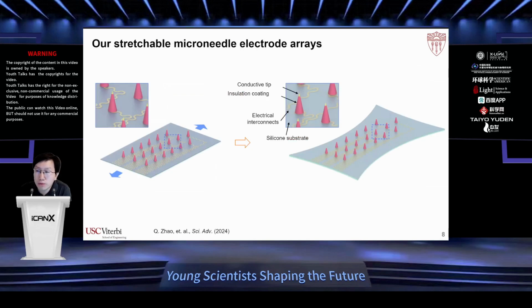Here we have an array of rigid microneedle electrodes with their tips exposed for targeted sensing and stimulation. And how can we make rigid microneedle electrodes stretchable? We use serpentine interconnects, which is a commonly used structure design in stretchable electronics. Each microneedle is electrically connected to a serpentine interconnect, which is then connected to external electronics. The microneedles and the serpentine interconnects are bonded covalently to a stretchable elastomer substrate, so that when we stretch, the serpentine interconnects can deform, rotate, and twist, while keeping the needles rigid and intact.